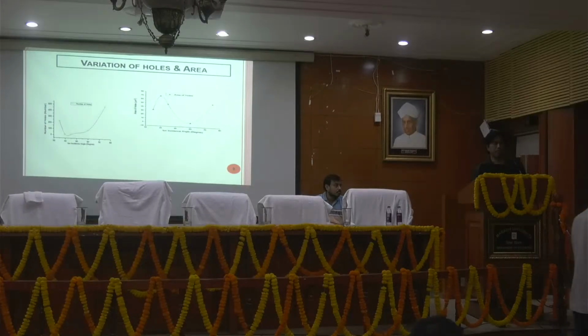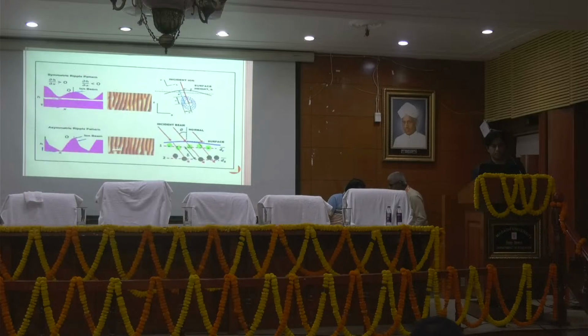Why are we using the area of the holes? Because we want to generate some 2D material layers on the silicon ripples. These ripples are used to create enhancement in the surface. We see in this dynamics, if the surface is flat, the area is small, and if the surface is of rippled nature, the area can be enhanced. That area can be used in various applications like gas sensor applications and corrosion inhibitor applications.